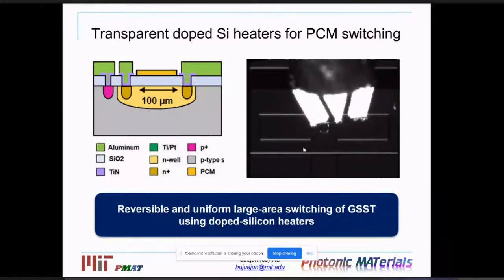Now, to show you how we integrate these devices into a reconfigurable photonic platform, I want to explain how we switch the phase of this material reversibly. The most convenient method for photonic integration is to directly use doped silicon as a heater, pass current through it, and then use Joule heating to trigger the phase transition. What we're doing here is essentially controlling the duration and amplitude of the voltage pulse. We can control whether we are crystallizing the material or amorphizing the material.